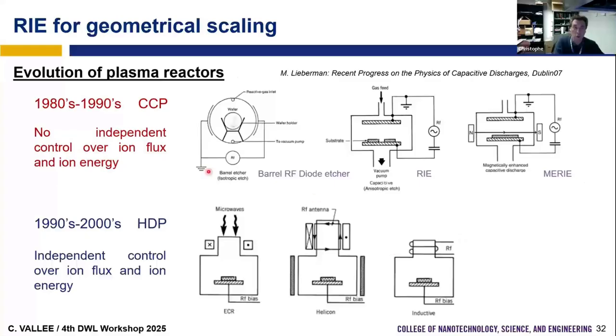So this is a slide just to show the evolution of this plasma etching reactor during this first scaling era. So we went from the first design with a single frequency CCP reactor that can be magnetically enhanced, to have more uniform plasma potential and etching rate on the wafer. And now we have the second generation of plasma etching reactor, which are HDP source, where we have, for example, an inductive source, where we have an independent plasma density with the source power applied to the coil, and the bias power applied to the substrate. So this is the second generation of plasma etching reactor, HDP source.